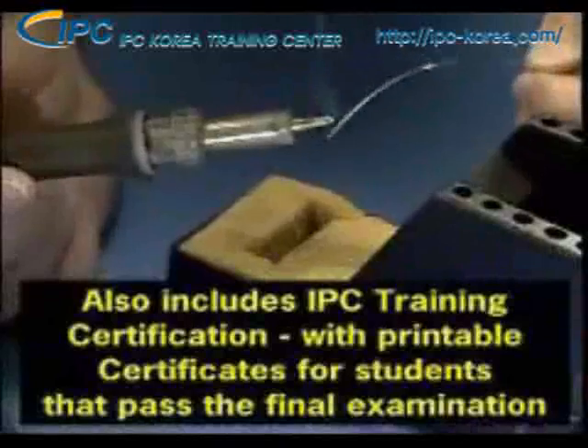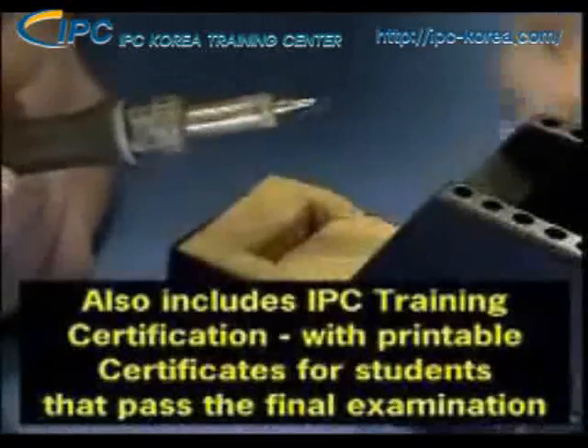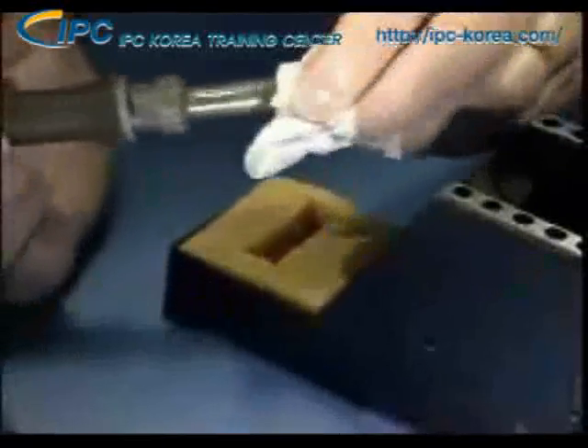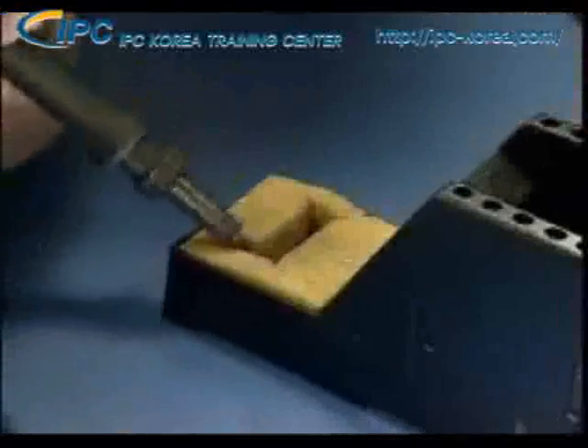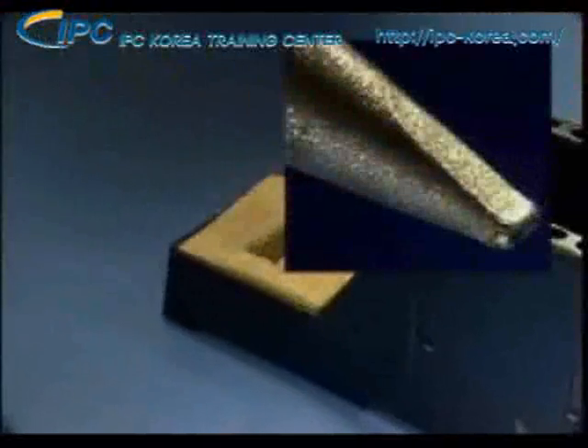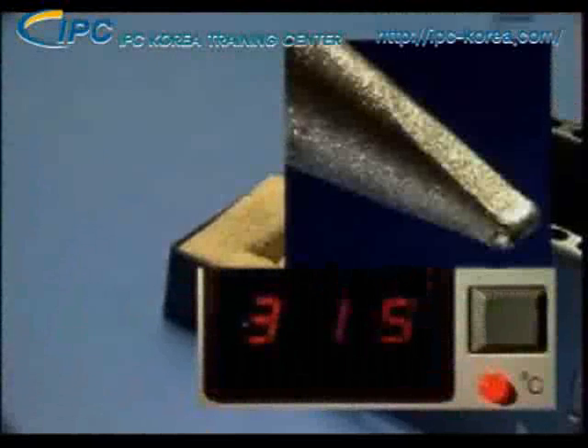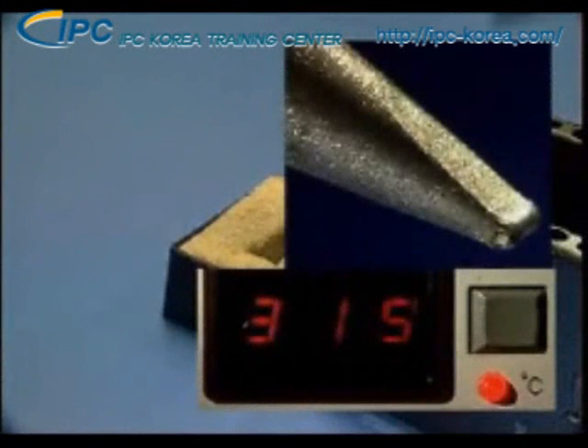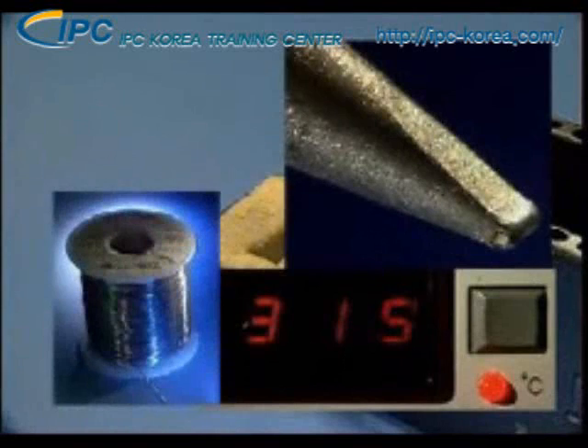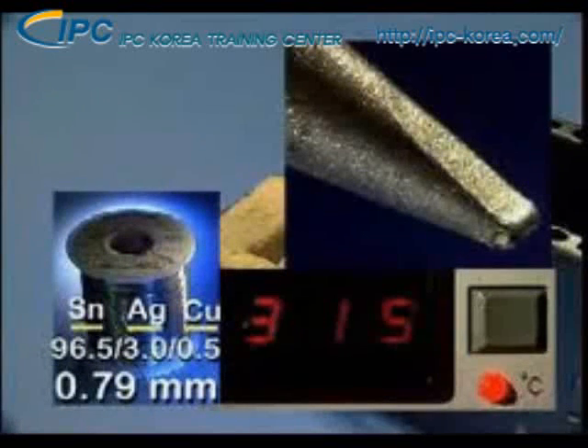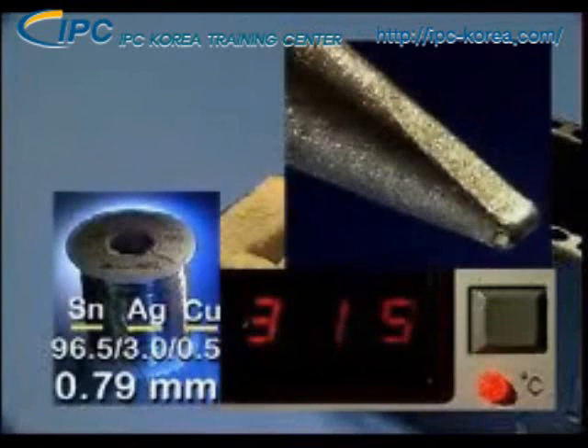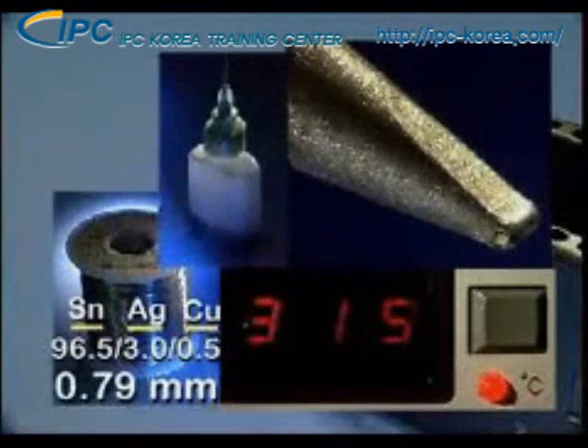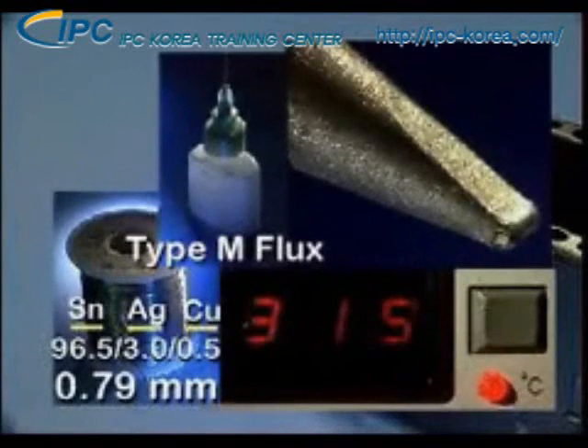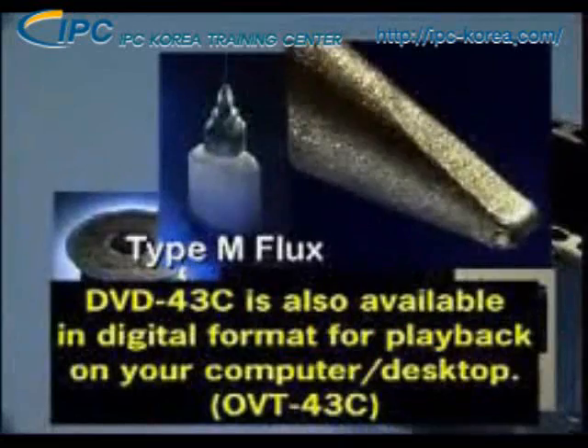After we've prepared the tip of the soldering iron, we should be ready to start the soldering operation. We'll be using a temperature-controlled soldering iron with a chisel tip. The temperature of the tip will be set at 315 degrees C. Our solder will be 96.5% tin, 3% silver, and 0.5% copper, with a 0.79 millimeter diameter. The flux in the core of the solder will be type M, or medium activity.